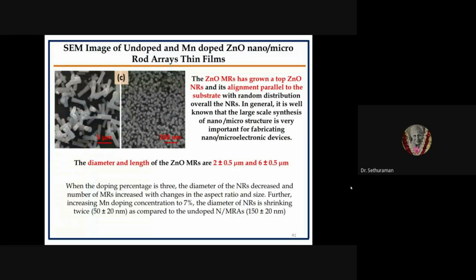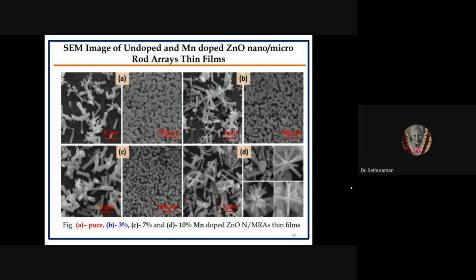I told you that when we are slightly increasing the doping value, in the case of the pure one, and in the case of increasing the element doping, we found that more micro assemblies are formed on the surface of the vertically standing zinc oxide nanorods. Further increasing the doping gives more microrods on the surface of the nanorods. Finally, the nanorods are completely destroyed.